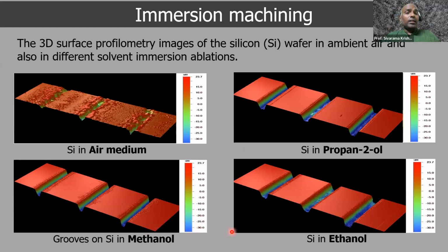In one sense, this sort of rugged, the ridge structure with this very ill-defined surface is formed in air because of the fact that even in the femtosecond machining process, there is some debris, and unless we have a nice way to remove the debris as the process is happening, it's not going to give us the best results. And the liquid sets up a convection, and that convection takes away the debris efficiently, and also seems to regulate the thermal balance in the process well. It's not something we completely understand. We are actually taking to some modeling of the process using COMSOL, which is still work we are going through, and hopefully we'll have some results to report about that.